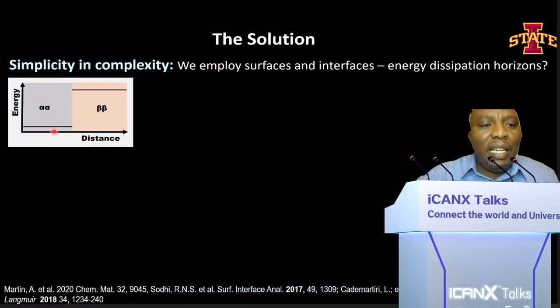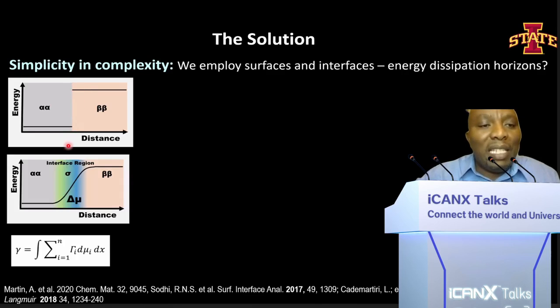We rely on looking at material interfaces. And if you think about a material surface, it's basically the boundary between phases. If you take it as nothing more than a surface, then you have a thermodynamic challenge, because you are assuming that at that point in the material, you will have two energy states, which is impossible. So the better way to look at a surface is actually to look at it as a gradient in composition. And we see this manifested in the way we define surface tension. We define surface tension as nothing more than the summation of the interfacial excess and the change in your chemical potential. And here I add dx because there's a dimension associated with that. So I argue that surface tension should actually be a multi-dimensional component rather than a scalar component.